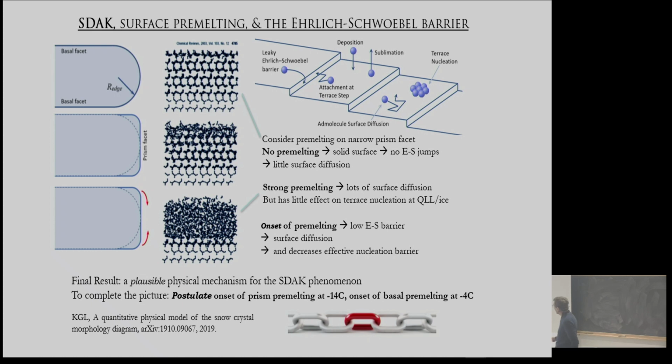You're going to squirt a little extra on, it's just not going to do much. But there's an intermediate where it's like this. There's not too much there already, and if you now allow some of these molecules to spill over, you might have enough molecules to reduce the nucleation barrier, and it'll grow faster. And that's just at one specific temperature that's going to happen.